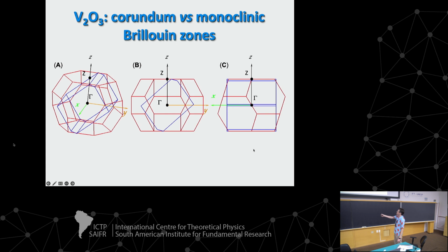So red is the paramagnetic Brillouin zone. Blue is the antiferromagnetic Brillouin zone. We measure along gamma z. So you see, the change in Brillouin zone is tiny. That's why we choose to do that. In principle, the effects of antiferromagnetic folding in our data are minimal or impossible to detect experimentally. But on purpose, we chose that for many technical reasons. One being that we didn't want to complicate the observations with many other changes. Right now, we are measuring in the basal plane. So we are trying to see now what are the explicit effects of antiferromagnetism. We mean the students. Exactly. We is the royal we.